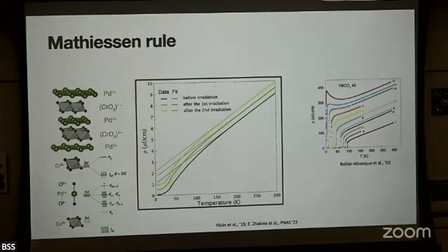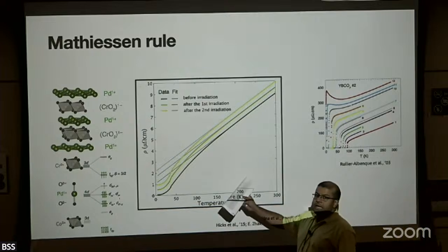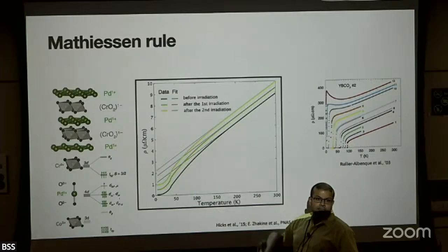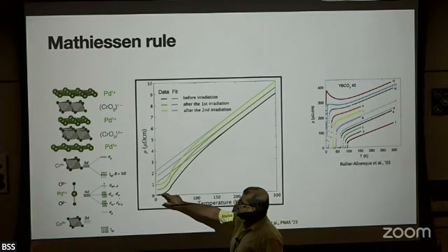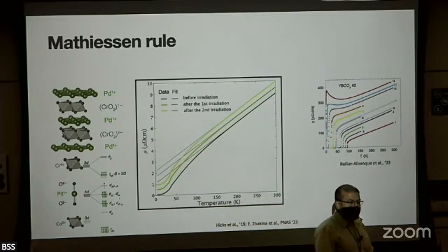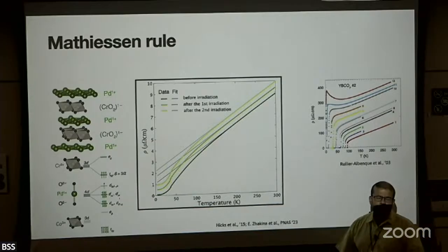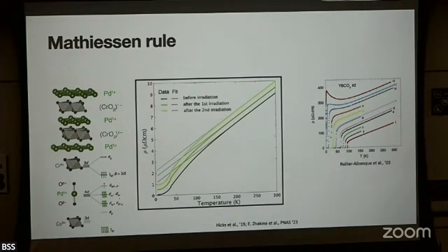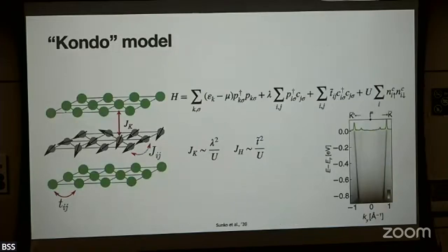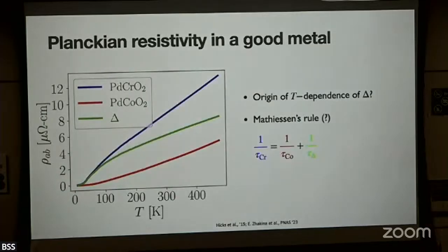And generically, you might have thought that it would completely screw up the temperature dependence of the resistivity, but this is what happens. As you increase the dosage of radiation, all that it does is just shift, only changes the elastic contribution, which of course you expect to change if the impurities are changing. The slope remains the same. By the way, this is something that has been seen also in the cuprates. This is YBCO, very old data. So there's some similarity between the two sets of results. Not to say that what I'm about to tell you in delafossites has any bearing on cuprates, but still worth noting.